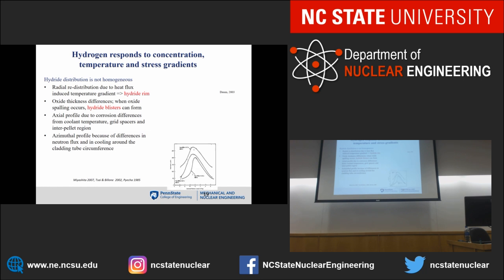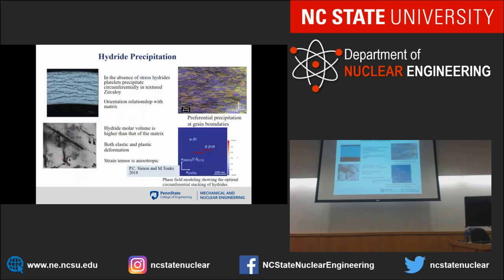Now, this is also from work that Mike Ballone did. It shows hydrogen content as a function of the azimuth, as a function of 2 pi. So if I do the PIE, I took a ring like this and measured it in a LECO system, and I got about 600 ppm, but it might be 800 here and 400 here. The 400 we don't care about, but the 800 is what's going to cause failure. So it's the concentration.